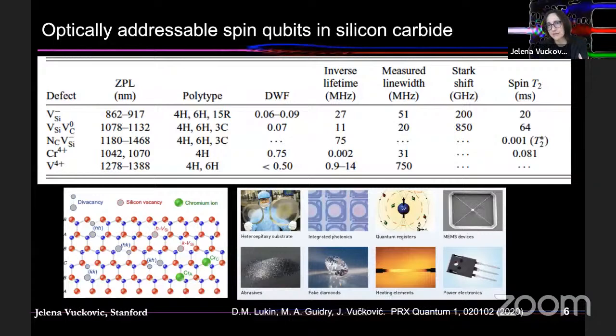And silicon carbide is very exciting for a variety of reasons. It's a few orders of magnitude cheaper than diamond, and that's why people use it to make fake diamonds. You can get it on 6-inch wafers from companies. Also, it's being used for MEMS devices, power electronics, heating elements, even abrasives. So it's really a material that is very available, and you can get it in high purity relatively inexpensively. But it also hosts a variety of interesting color centers that people have worked on.